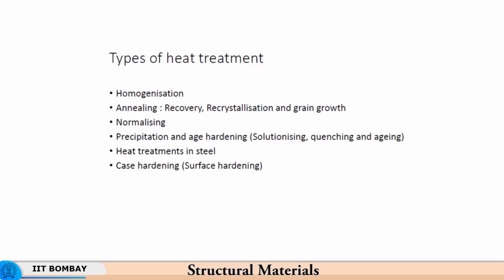Solutionizing has great limitations in terms of the hardness that can possibly be obtained. So, what you do is that you heat it in a controlled manner. Heat it at relatively lower temperatures for a controlled period of time, so that you allow a controlled amount of diffusion to take place and for certain phases to form. You know which phases are favorable to give you greater hardening, greater strength. So, you have that heating rate, that heating time, the holding time at the temperature at which these intermetallic precipitates would form and then get precipitated all over the material.